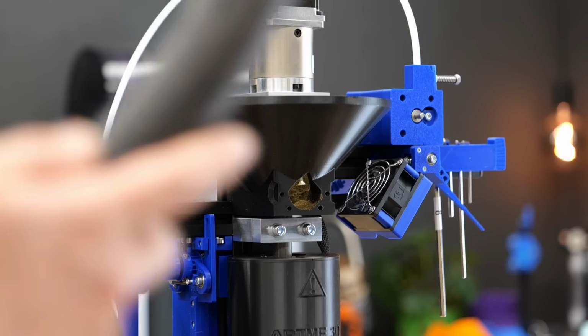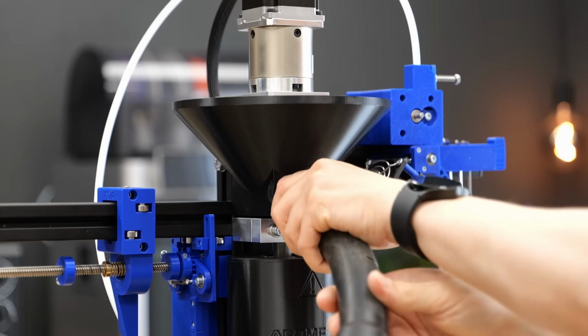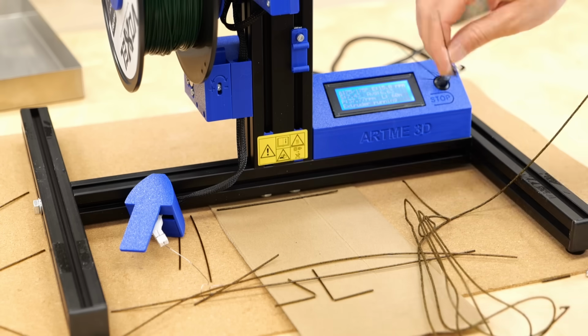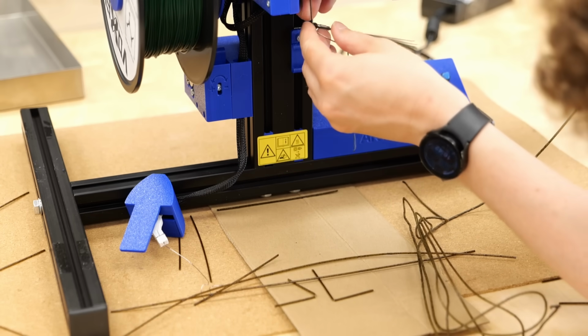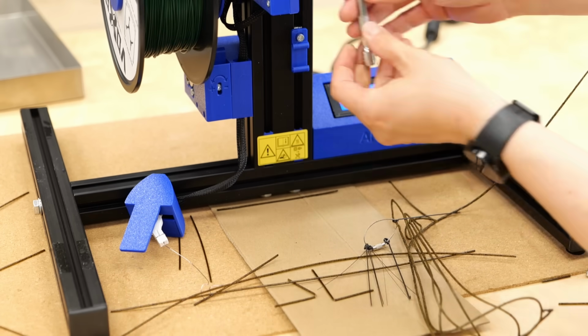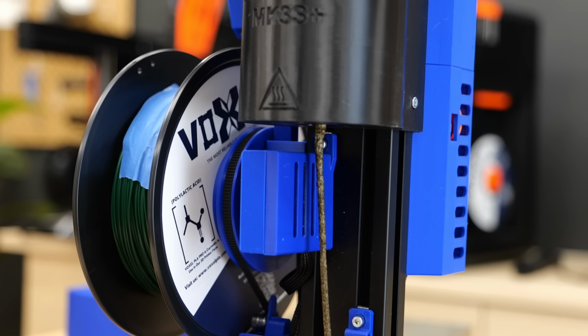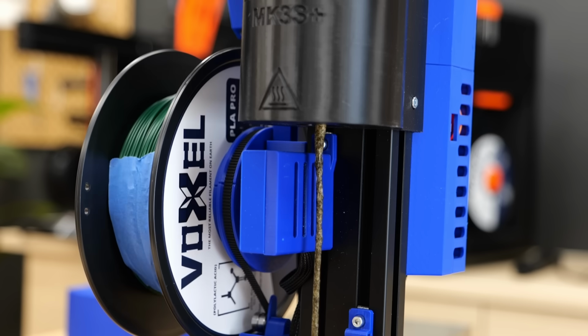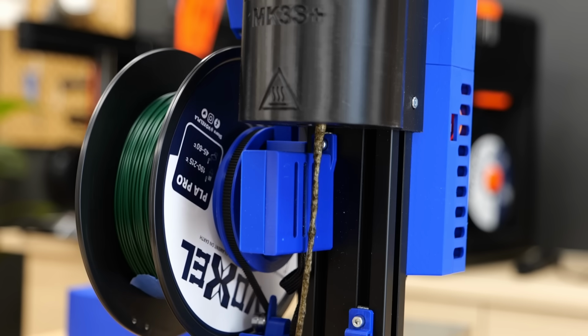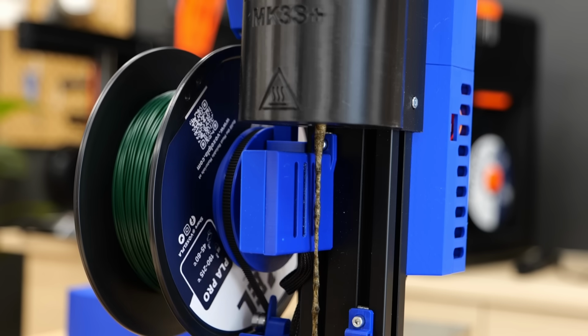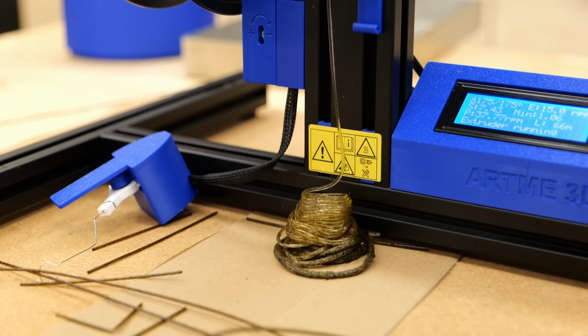I vacuumed out the rest of the material to make sure that no more filler was dragged into the extruder, and when I wasn't even able to clear the clogged nozzle with our nozzle pokers, I ultimately had to unscrew the nozzle and let the rest of the material purge out with new PLA pellets I fed from the top. Initially, the mix really foamed up once it left the extruder, but when all the clean PLA pellets finally purged everything out, the material was nice and clean again.